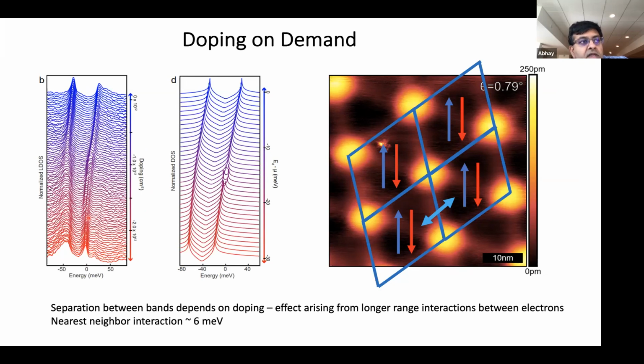Right. So in the original work by MacDonald, the prediction was precisely at the magic angle that you would have 2 Van Hoves that basically sit on top of each other. So they would form a single Van Hove, right? And then there's a gap to other higher subbands. Exactly. But this was within nearest neighbor tight binding, and there are many reasons why that would not be exactly true. So the real spectrum at the magic angle, as measured by us and now several other groups in STM, is that the separation between these 2 Van Hoves is not 0, but about 40 millivolts. That's the separation at the magic angle.